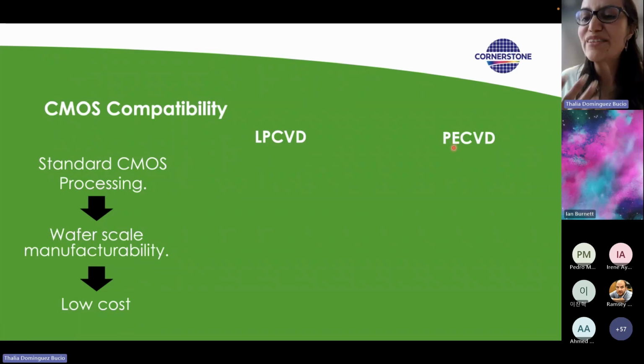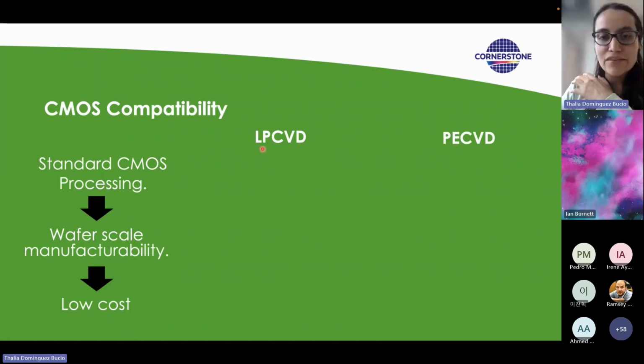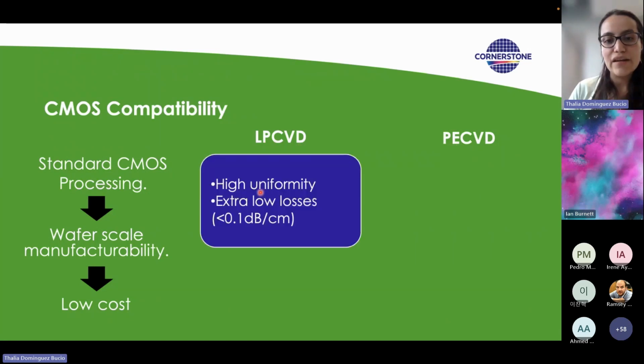Now, what's the difference between these techniques? This is something that is very important to understand, because the technique will determine some of the properties of the silicon nitride layers that we obtain, and that will determine for which applications each of these types of silicon nitride is more appropriate. In this case, if we talk about LPCVD silicon nitride, this silicon nitride is deposited in a furnace. In the furnace, we pump the gas, we heat it up at very high temperatures, and that's how we deposit our silicon nitride.